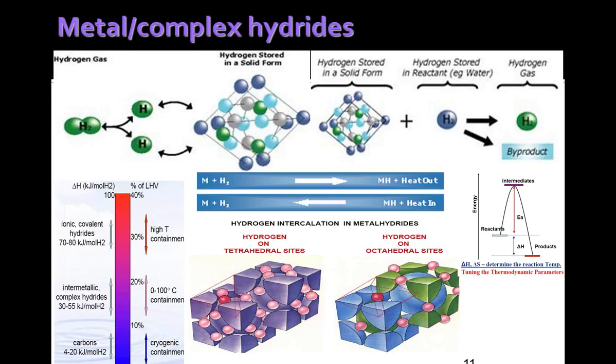And then the intermetallic hydrides, what I said about the lanthanum nickel 5 and iron hydride and all these, they do have hydrogen absorption and desorption at about 0 to 100 degrees Celsius. That means low temperature to room temperature. The delta H required for this is about 30 to 55 kilojoules per mole hydrogen. Whereas at higher temperature, where the complex hydrides work, the ionic and covalent hydrides, they have more than 100 degrees centigrade. It could be 200 to 300 degrees Celsius.